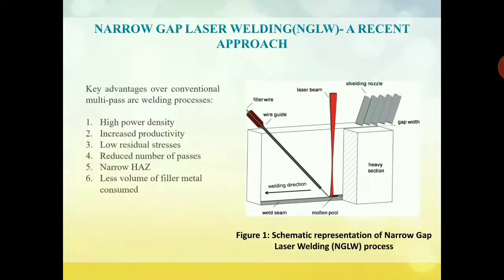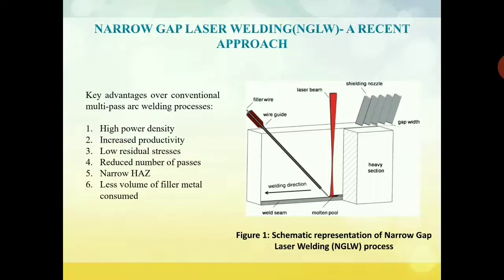Some key advantages of NGLW over the other joining techniques are that it allows high welding speeds owing to its high power density, thereby resulting in increased productivity. Consequently, the distortion and residual stresses are lower due to low heat input. Moreover, this technique produces a heat affected zone that is narrow due to the narrow bead width. Besides steels, NGLW has proved promising for welding aluminum alloys, nickel superalloys, and titanium steel bimetallic sheets.